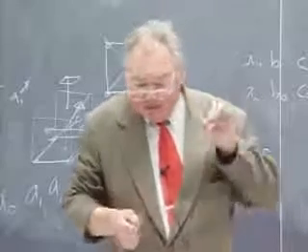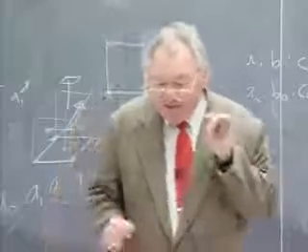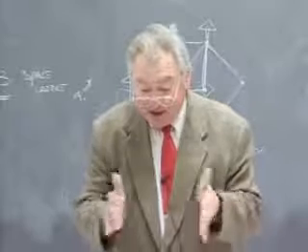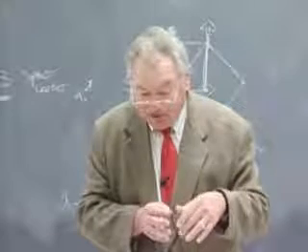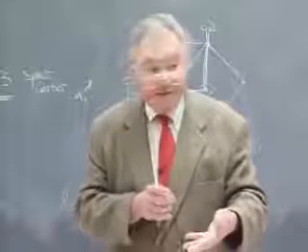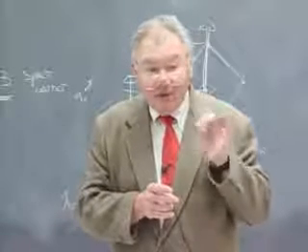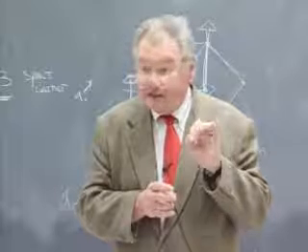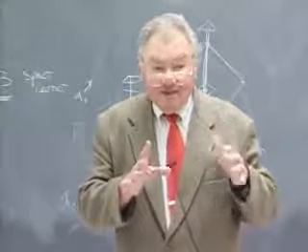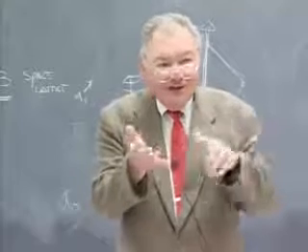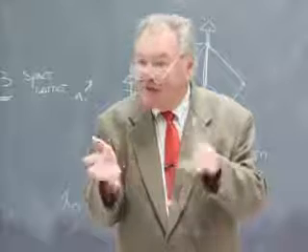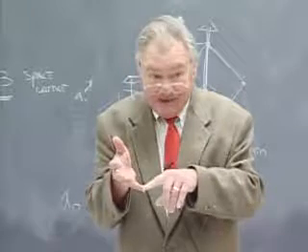So let me now just quickly say that if we have derived the lattice types, and by implication the space groups as well, for a 2-fold axis, for a 4-fold axis, for a 6-fold axis, and so on, we have automatically satisfied the requirements for any point group that results when you add inversion to a 2-fold axis, a 4-fold axis, or a 6-fold axis.